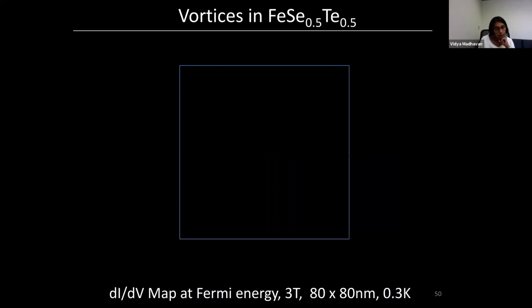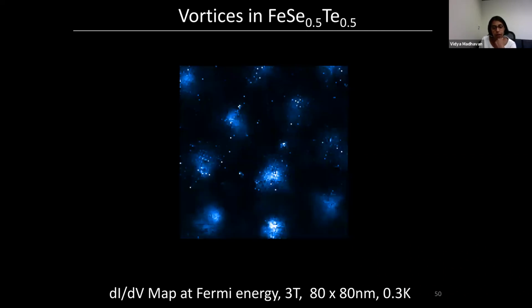And now let me turn on a magnetic field. Now I'm going to measure the density of states exactly at 0 bias, and that's what it looks like. So suddenly, in the presence of a magnetic field, you have all these bright dots. Each bright dot is a position where the magnetic flux has actually managed to penetrate through the sample. So inside each of these bright dots, this is called a vortex core.